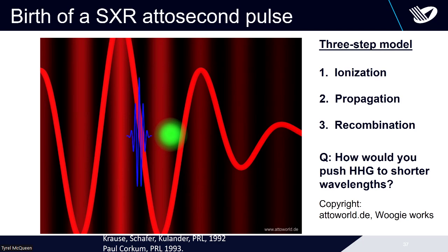What you can do is increase the cycle duration. What that actually means is you go to a longer wavelength. If you do that, there is more time in an electric cycle for the electron to pick up kinetic energy, and then upon recollision, you get higher energies out. So it's a bit counterintuitive. You have to go to longer wavelengths with your fundamental driver to get shorter wavelengths out. The problem is if you do that, the flux goes down. So there is no free lunch here, unfortunately.